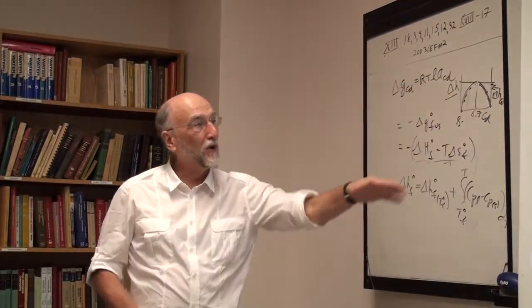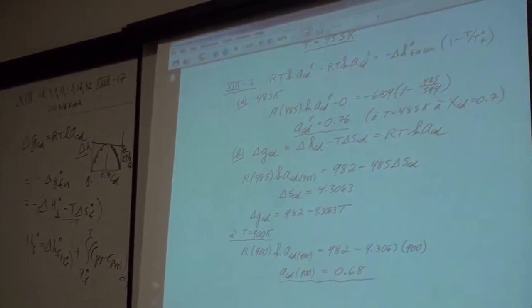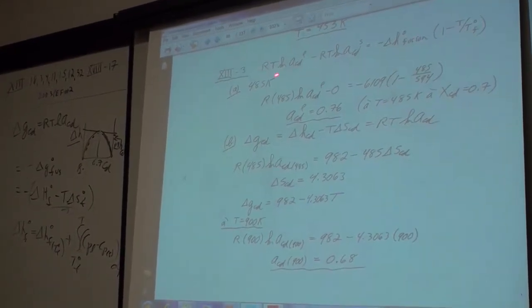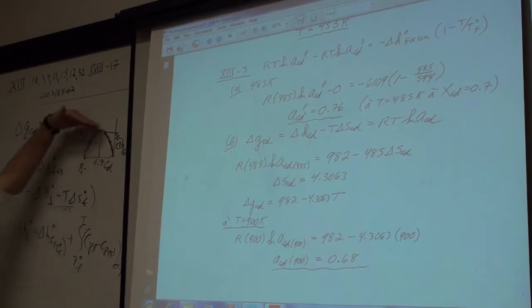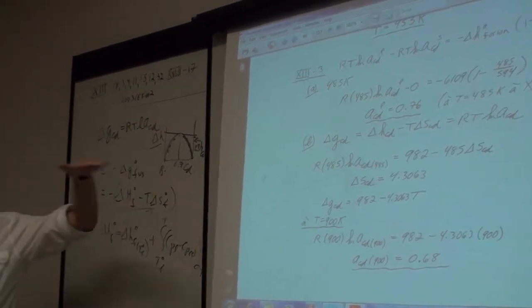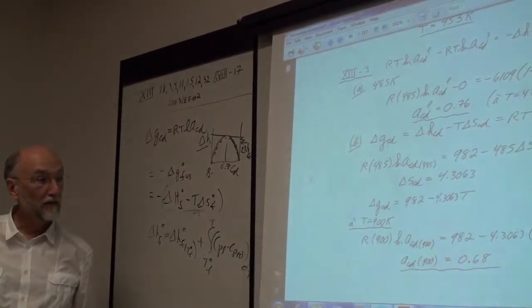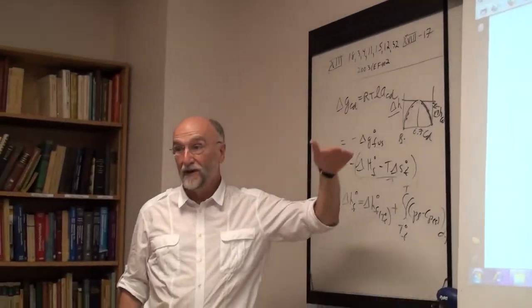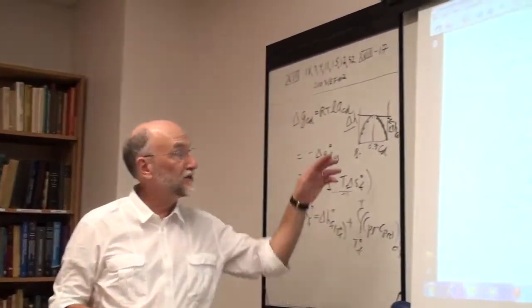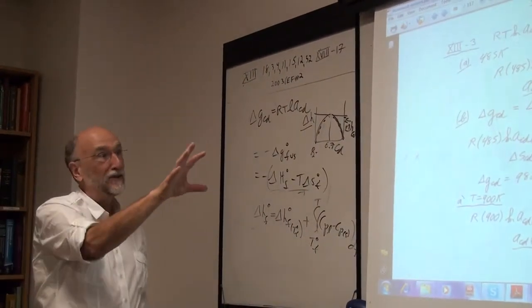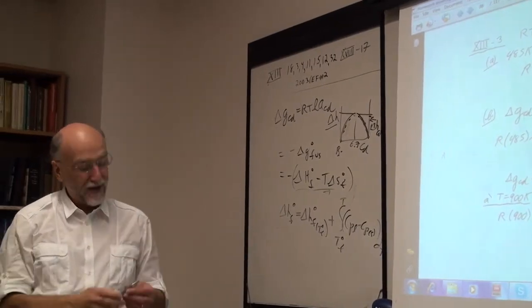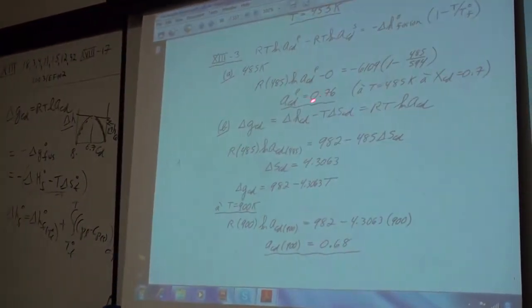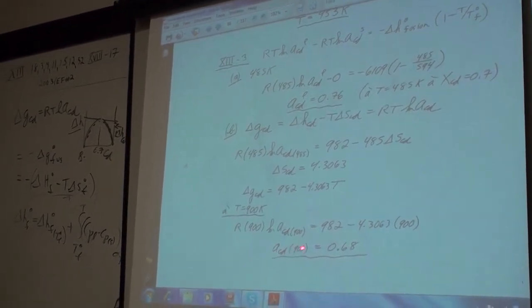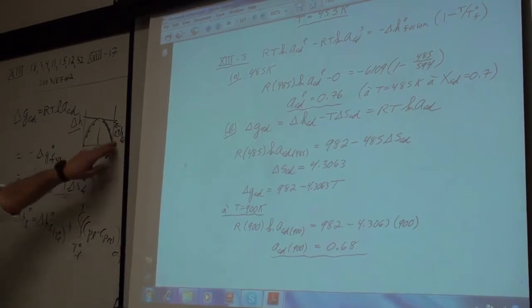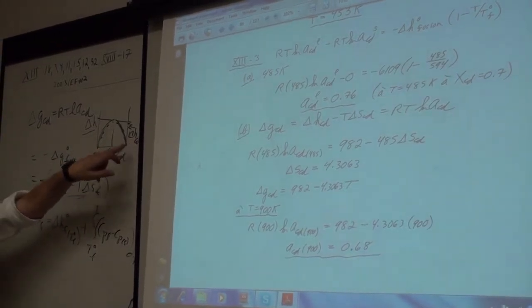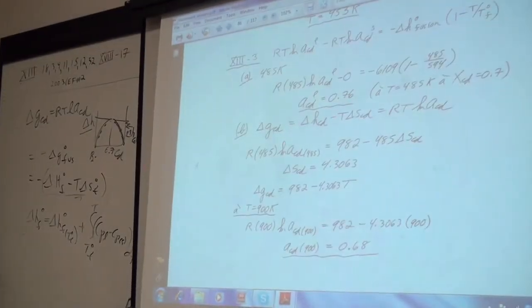You can't get around that. What you're doing is at every point on the liquidus, you're using this equation, or the computer is using this equation, to get the activity on the liquidus, and then it's using the partial heat of mixing in order to integrate up in temperature to get you the activity or partial Gibbs energy at the higher temperature. This is what's really happening. If you're trying to judge the error limits, even though the computer doesn't do it exactly this way, what it's doing is exactly equivalent to this. If you want the error in calculating the activity at 900 relative to the activity at 485, it's based entirely upon the accuracy of this delta H cadmium term. That is the term that's going to determine the difference between these two things.